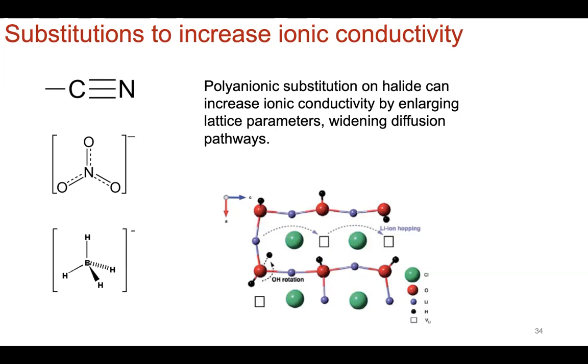So in terms of substitution and also engineering higher ionic conductivity, some of the methodologies that we've talked about, the strategies of substituting the anion site to increase and widen the diffusion pathway to increase ionic conductivity. Same is done here in terms of either introducing vacancies so that the hopping is faster, or these anions like the cyano group or the NO3 group or the borohydride group to open up the diffusion pathway. Also have been attempted and are still ongoing, because this family of compounds is quite nascent relative to all the other family of compounds that we talked about.